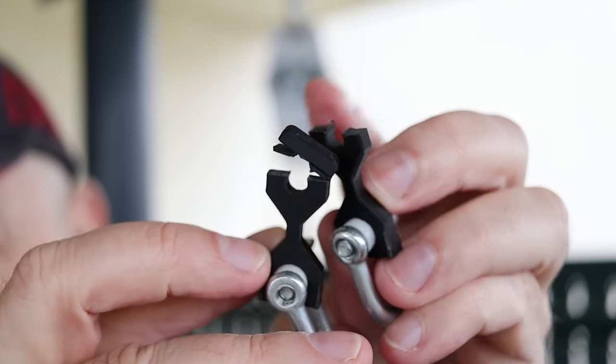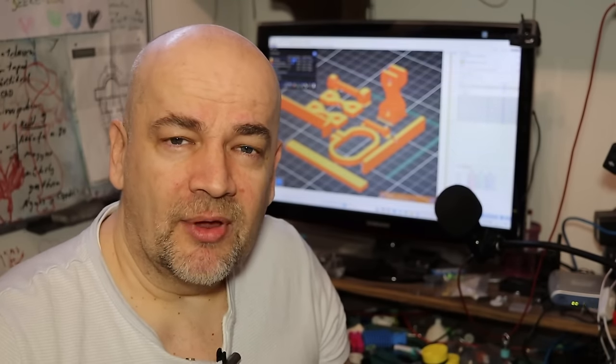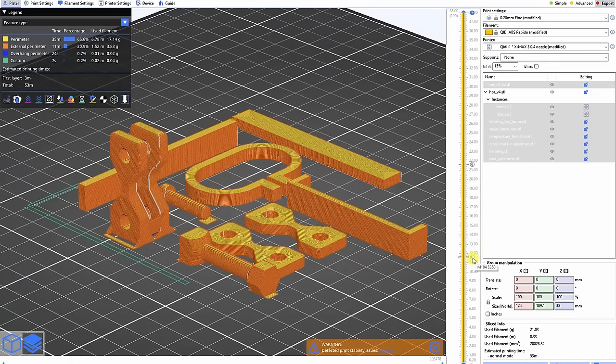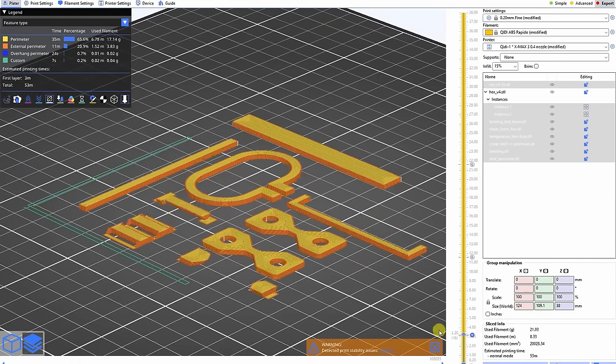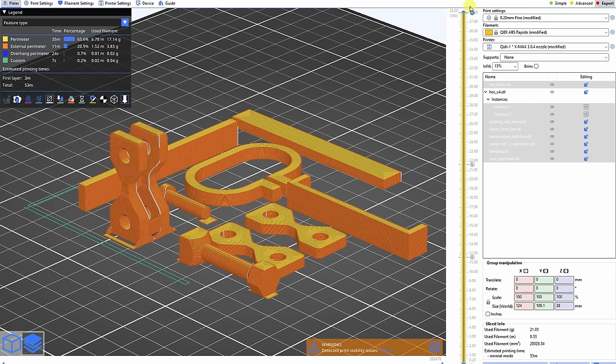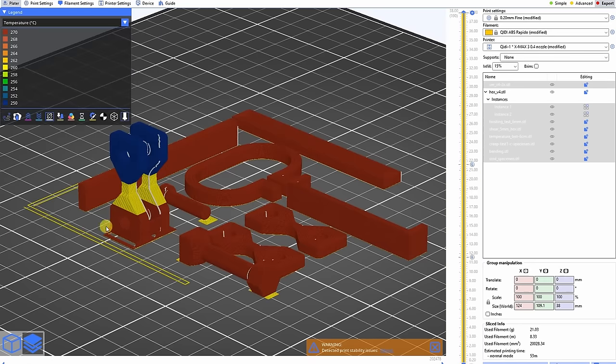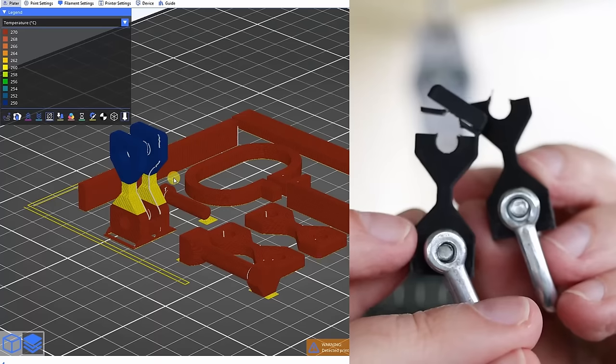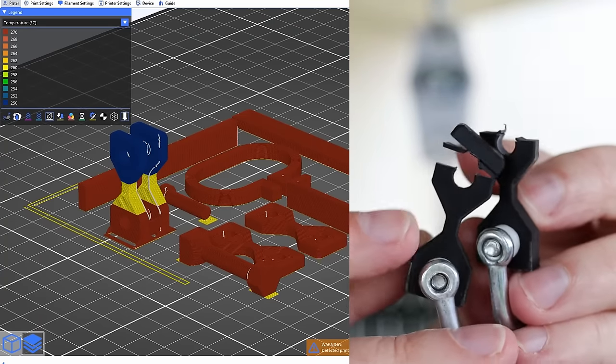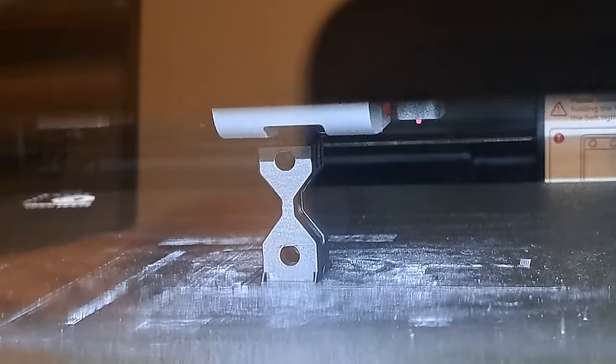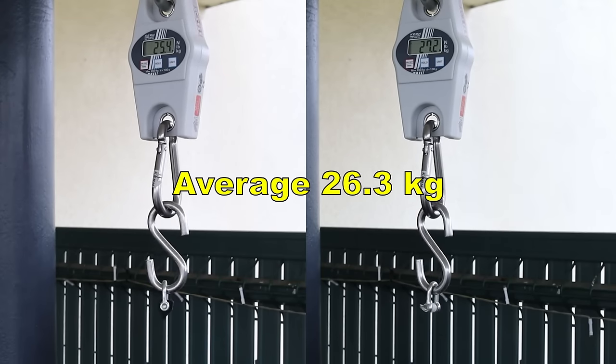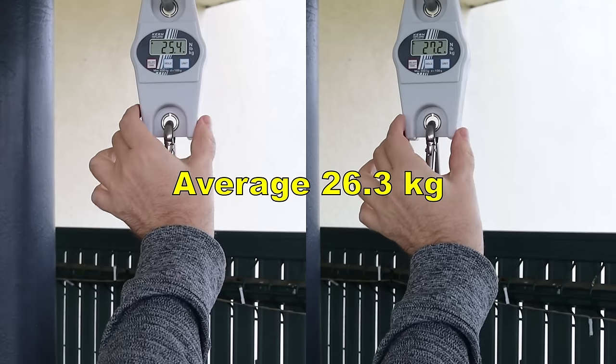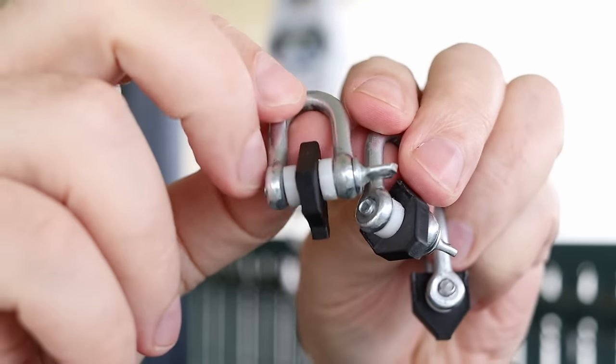I find this layer adhesion a little bit weak so I checked my settings and I have to admit that I did a very stupid mistake. When I prepared the temperature tower there were those codes for temperature changes on certain layers, and when I prepared the test objects I just deleted the temperature tower, inserted new test files and sliced that object. And I forgot to remove those codes for the temperature change. Most of the test specimens are not affected by this except for the layer adhesion because actually the top of that test object was printed on 250 degrees Celsius so 20 degrees lower than the base. And I noticed they broke exactly where the temperature was 250 degrees Celsius. So I have to reprint these two test objects. And this time the break was on higher load and they broke correctly on the smallest cross-section area.